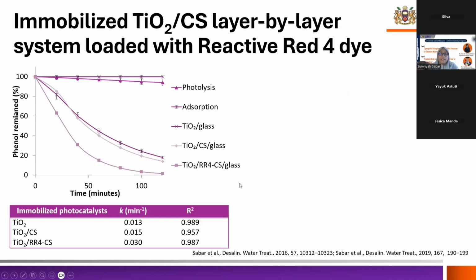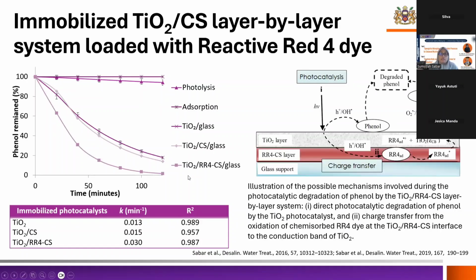To avoid any other adsorption occurring on the surface of the photocatalyst, we use phenol as the model pollutant. So in this case, we observed that the adsorption is poor on the photocatalyst because phenol does not have a good adsorption on chitosan. And we observe that in the presence of the dye, the degradation was much better as compared to TiO2 chitosan only. So this supports our prediction that there is actually a charge transfer occurring in the presence of the dye in the chitosan layer.